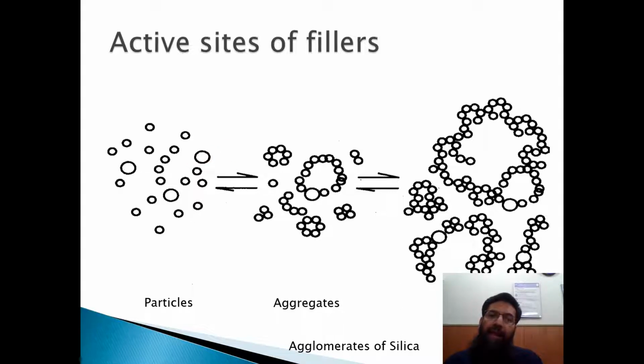And the hydroxyl site is the more interacting site because it can provide the hydrogen bonding, and the physical interaction of hydrogen bonding is the more active bonding or interacting site, due to which there would be more formation of the aggregates and agglomerates. If I compare the silica with the carbon black, I can say there will be more hydroxyl groups on the surface of the silica as compared to carbon black.